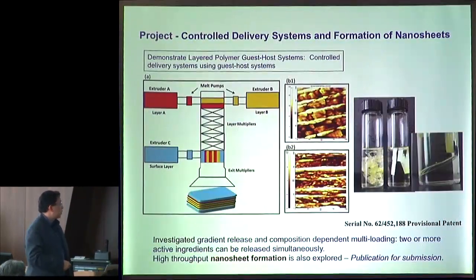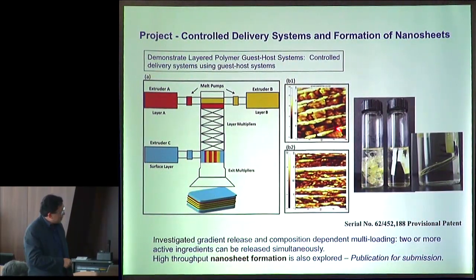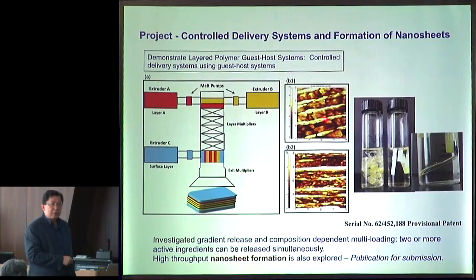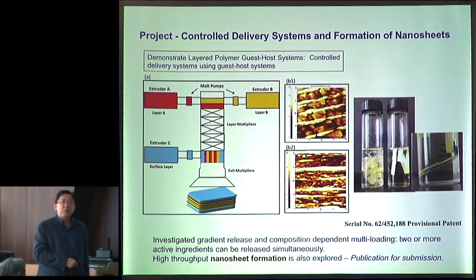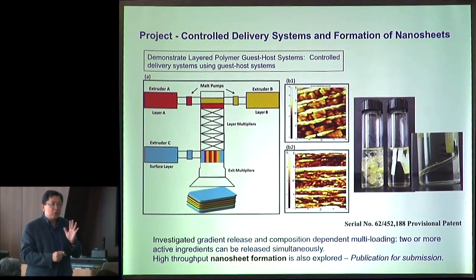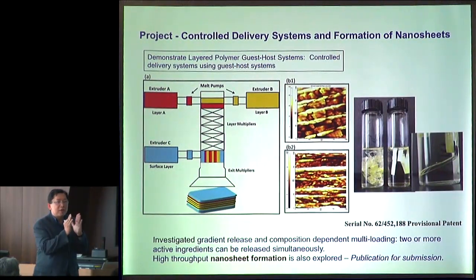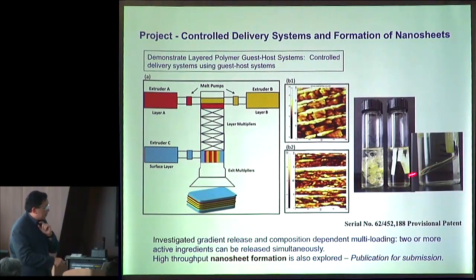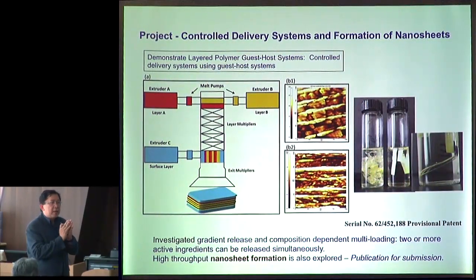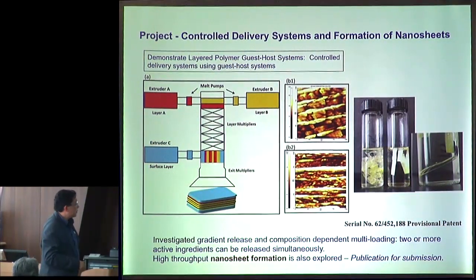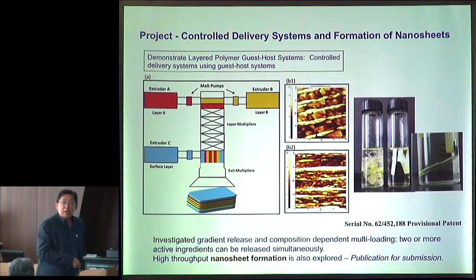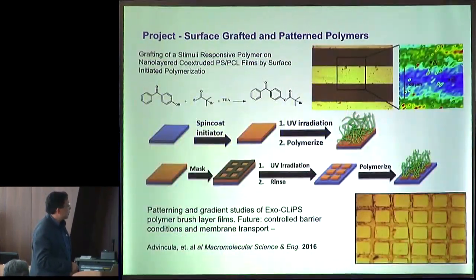So first project, we have done, for example, nanosheets by basically making layers of polystyrene and polyethylene oxide, or polycaprolactone and polyethylene oxide. These layers were put on water. What happens? PEO, or polyethylene oxide, is dissolved by water. So as the water dissolves the PEO, the sheets of polycaprolactone start separating. That's why we get these nanosheets. These nanosheets were generated from the separation of those layers by dissolving the PEO. And we have actually used them for drug delivery and controlled release type of studies.